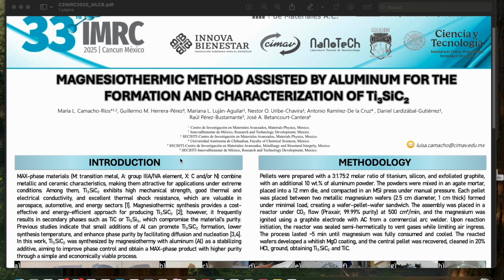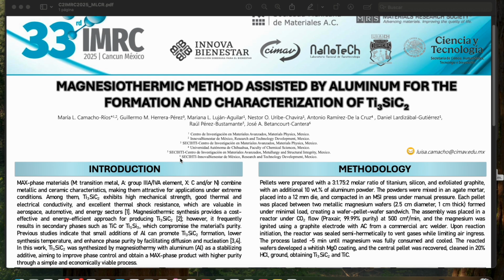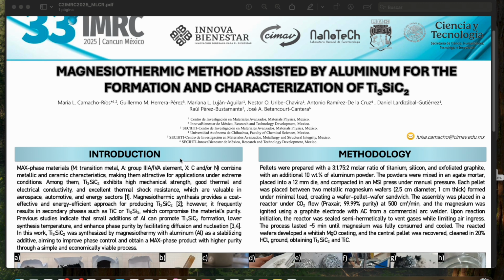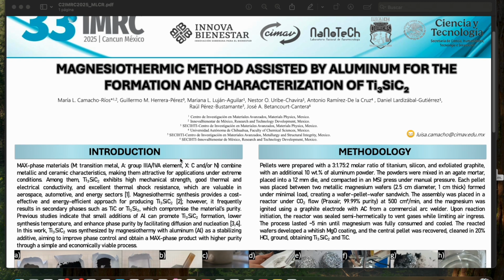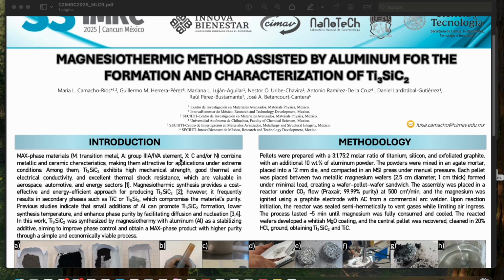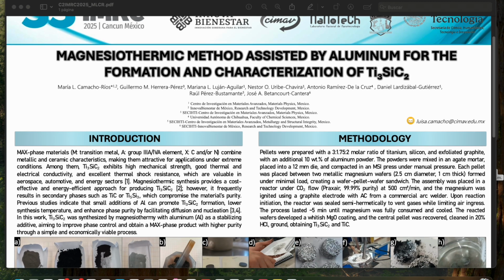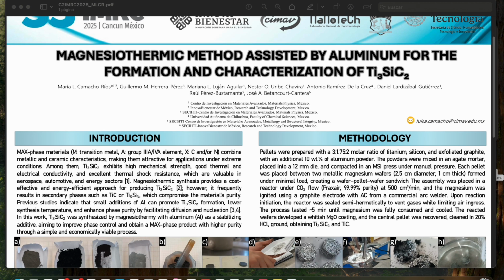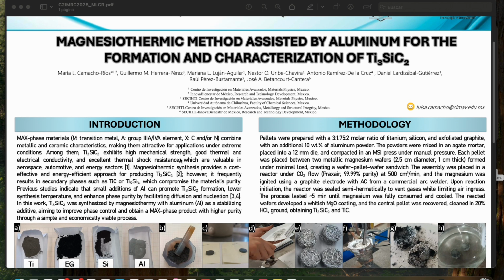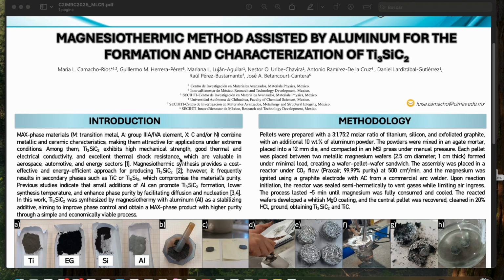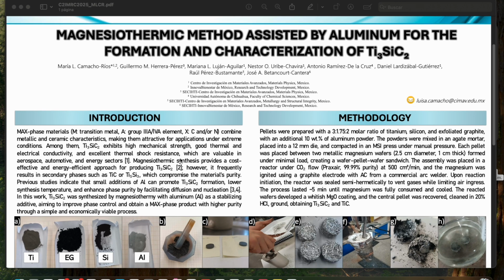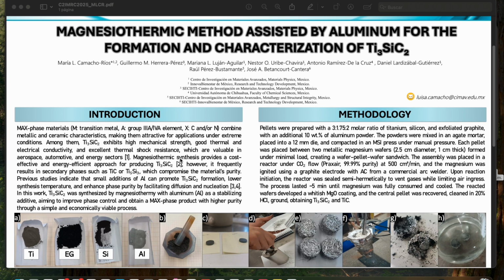This poster presents an aluminum-assisted magnesiothermic route that forms Ti3SiC2 MAX phase with higher phase purity in minutes, and explains why it works. MAX phases are attractive because they merge metallic and ceramic traits, yet conventional syntheses often demand long furnace schedules or hot pressing. Our goal was to keep the infrastructure simple, tighten the reaction window to about 5 minutes, and use a small Al addition to steer the path toward Ti3SiC2 rather than competing carbides and silicides.